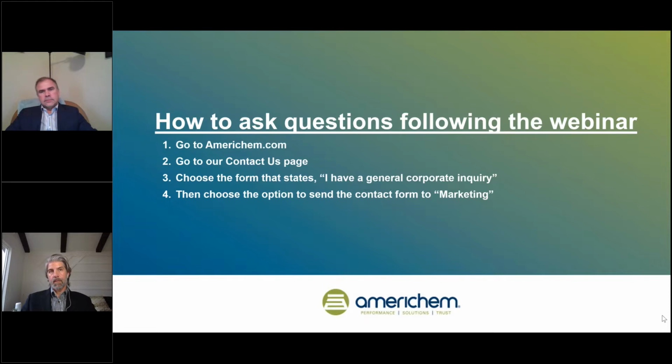Okay, next question is, do you have additives that can prevent carbonization during manufacturing? Would a hydrophobic be useful for this case? So carbonization, I tend to think of that as you're concerned with some sort of degradation effect on the polymer. That can definitely be addressed to some degree of efficacy through use of antioxidants. The carbonization, as I'm understanding the question here, is probably related to an oxidation of the polymer to some degree, probably pretty severe oxidation of the polymer.